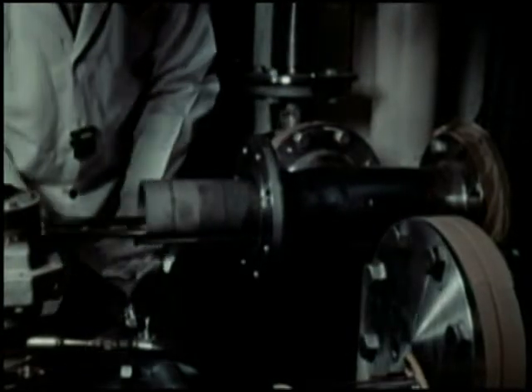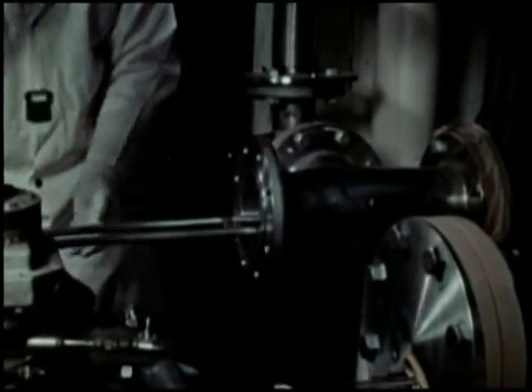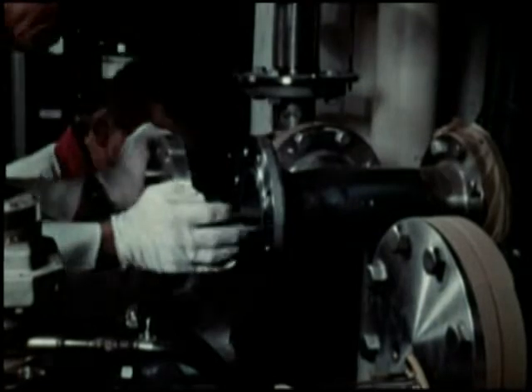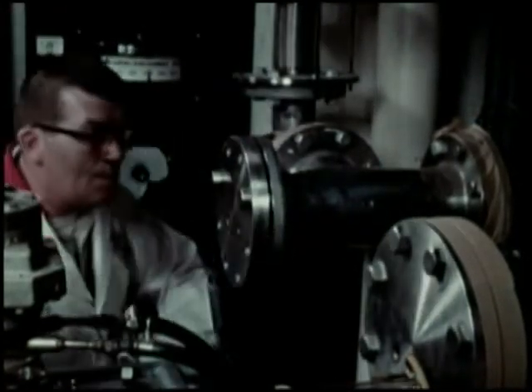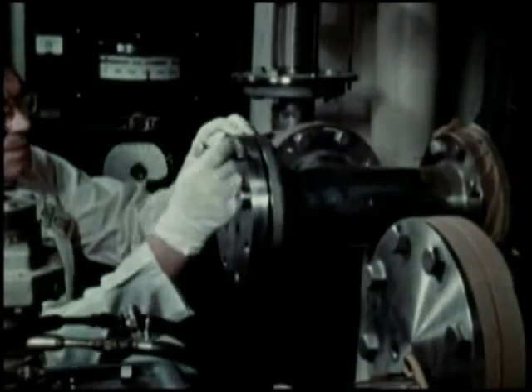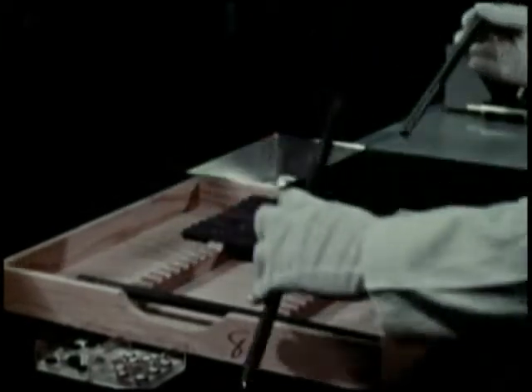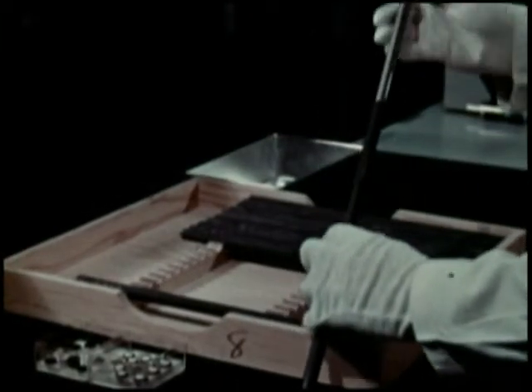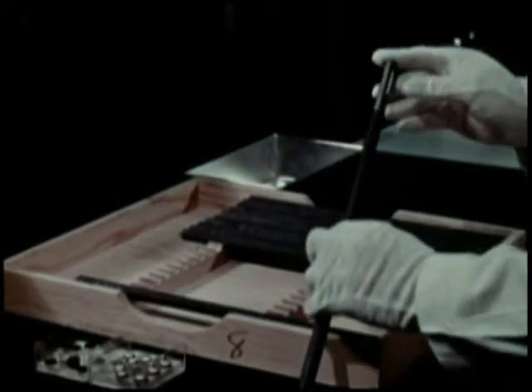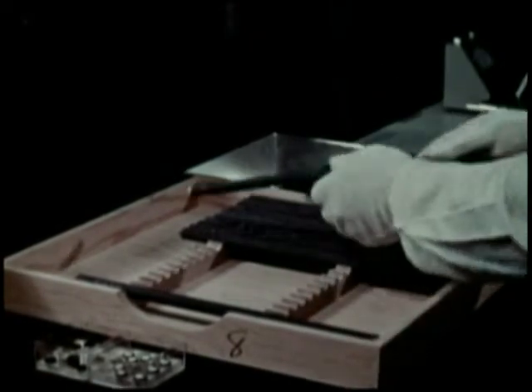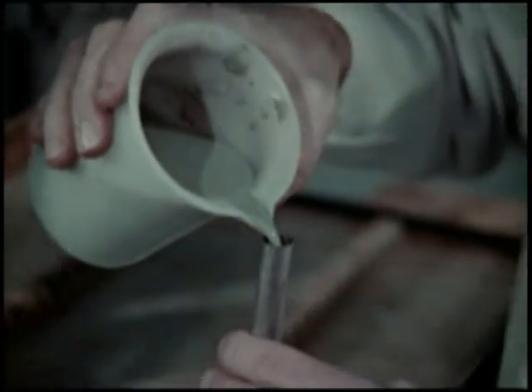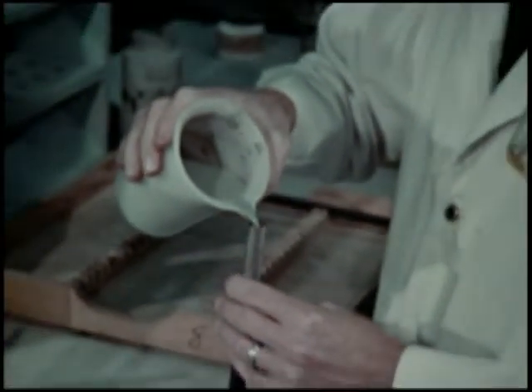The resulting hydrogen content of the material when at 1,300 degrees Fahrenheit is approximately that of ordinary water at room temperature. The hydrided rods are clad with chromized Hastelloy N tubes. To minimize hydrogen loss from the fuel at reactor operating temperatures, the internal surface of the cladding tube is coated with a thin ceramic coating.